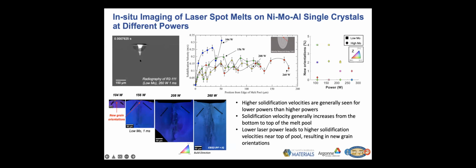We can see a lot of sloshing of the liquid metal in the melt pool, and we can see the progression of the solid liquid interface. Really the benefit is that we're able to pull out quantitative information about the solid liquid interface velocity from these kinds of experiments. Over here in the middle, we have solidification velocity versus position from the edge of the melt pool for different power conditions that we explored.